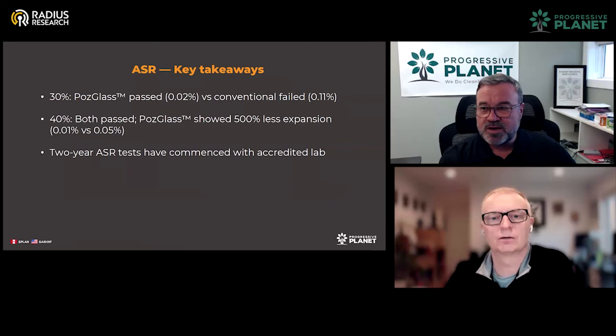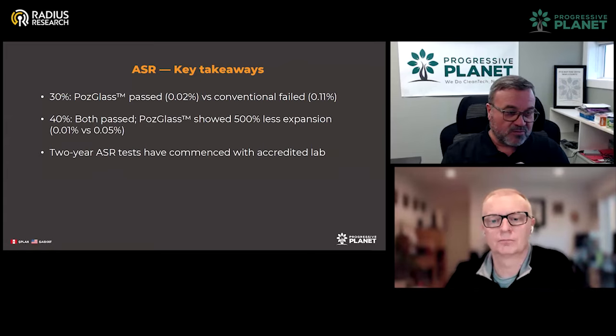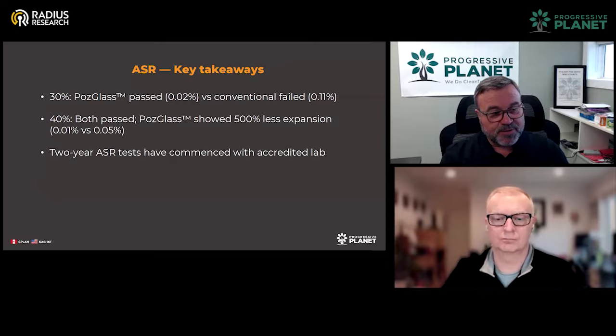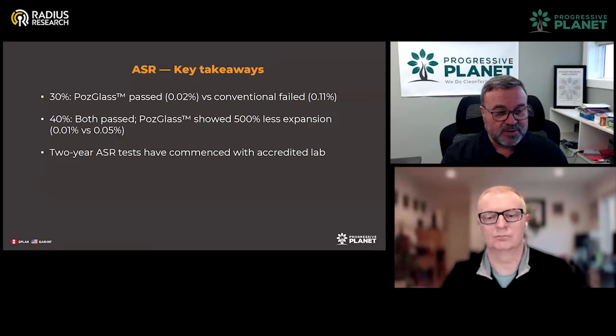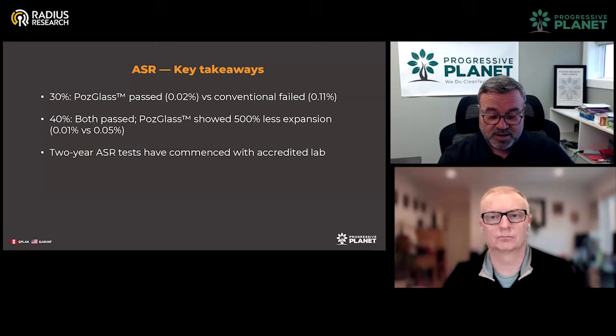So, summary key takeaways: 30% PozGlass passed, conventional failed; 40% both passed, but 500% less expansion with the PozGlass. And we have commenced with that same accredited lab 2-year ASR tests with both these size fractions of wet and dry ground glass pozzolan. So the PozGlass at 6 micron and 10 micron, and the dry ground glass pozzolan at 6 micron and 10. We've commenced the 2-year study. We've done the rapid study, and now we've commenced the 2-year. We're about a month into that study.